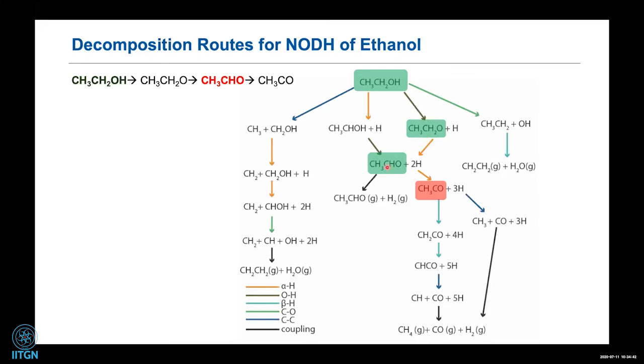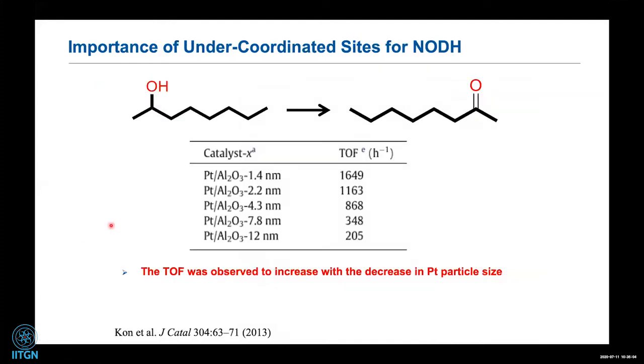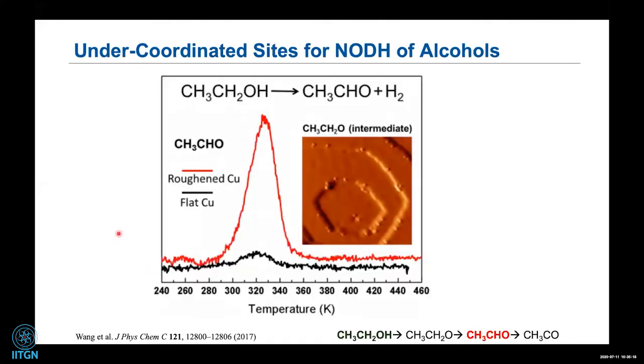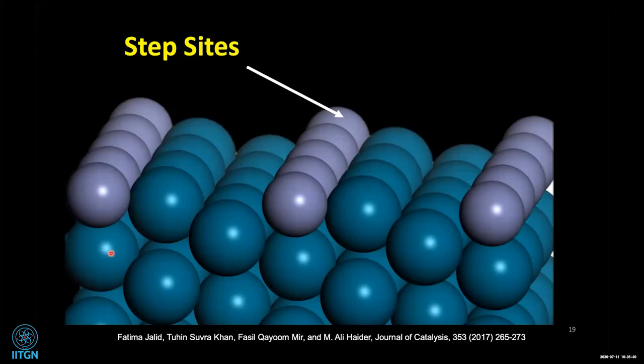The key route, highlighted in green, comes from modeling experience: ethanol first undergoes O–H bond scission to make CH₃CH₂O, and then an α C–H bond scission to make CH₃CHO — breaking the O–H bond first, then one C–H bond. Dehydrogenation of CH₃CHO gives CH₃CO. You need to tell the catalyst to selectively do this: first break the O–H bond, converting to CH₃CH₂O, then break the C–H bond to give CH₃CHO — stop there and do not go further. Structure sensitivity is evident from experiments: reducing particle size increases turnover frequency, and roughened copper surfaces with edges or steps show much higher acetaldehyde yield.